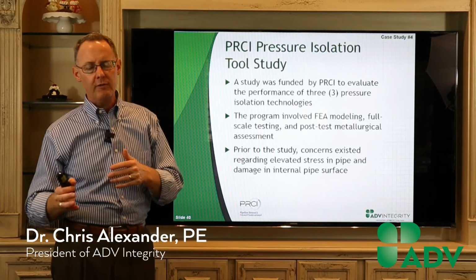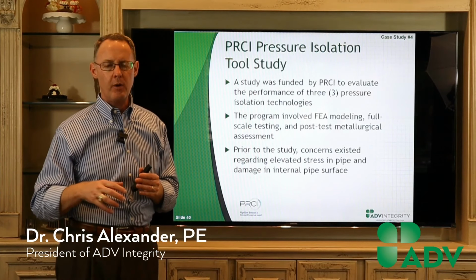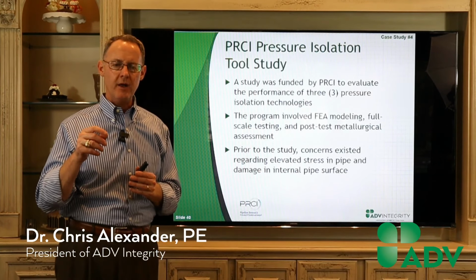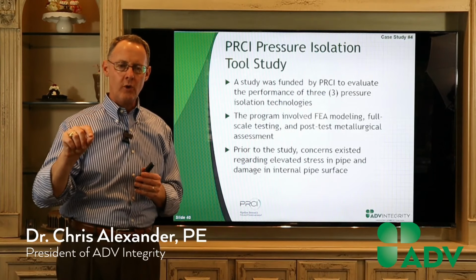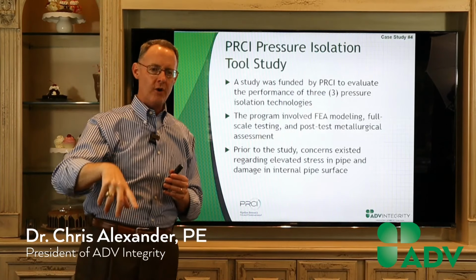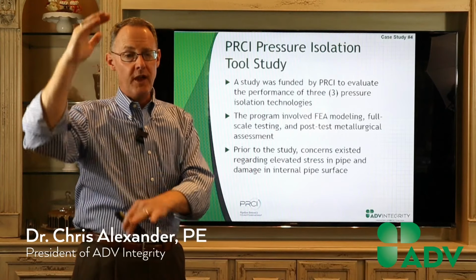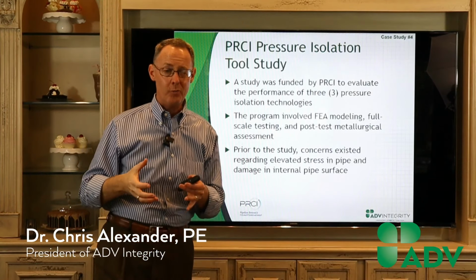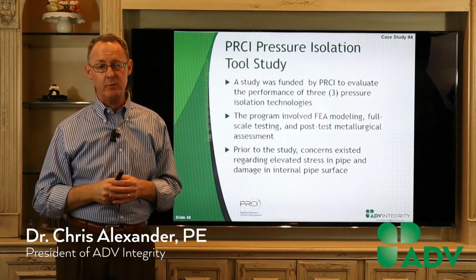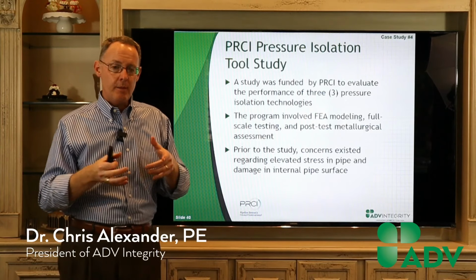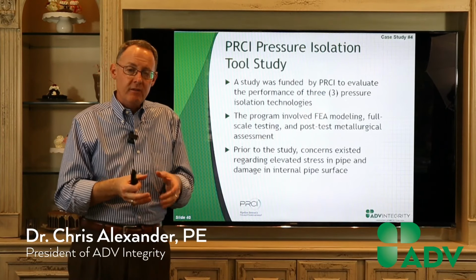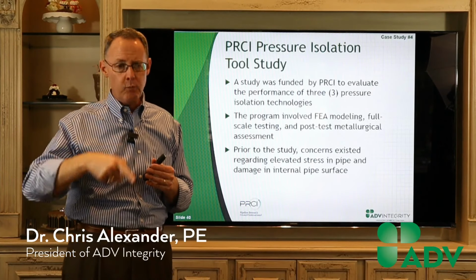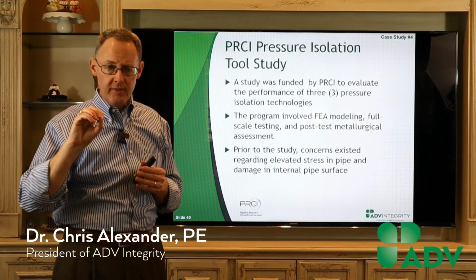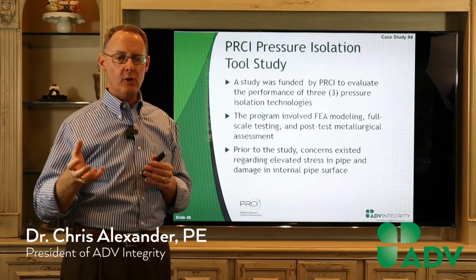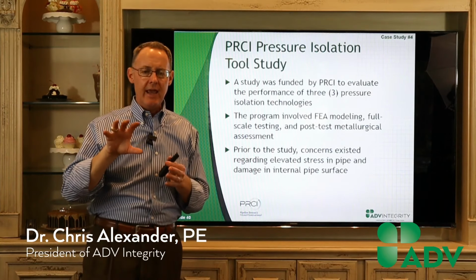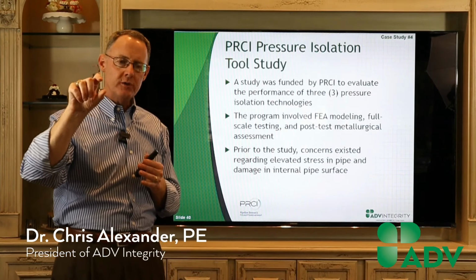A good rule of thumb for external pressure, and it's off a little bit, I'm probably within 15%, is about half a pound per square inch for every foot of water depth. So for example, if I go to 4,000 foot water depth, the external pressure is roughly about 2,000 psi. So I have to design my pipeline system to do that. The advantage for these tools going deep water is that when they seat, they don't have to worry about generating high stresses in the pipeline because the wall is relatively thick.